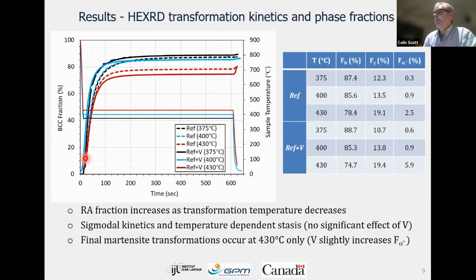That's quite clear. There doesn't seem to be a very strong effect on the kinetics of that transformation. It's pretty much complete by 180 seconds in all cases. The dotted lines here are the reference steel, and the solid lines here are from the steel with vanadium. So all you can really say is that at the end of transformation, the amount of bainitic ferrite, or conversely, the amount of retained austenite, is essentially the same. It's unchanged by the presence of vanadium.